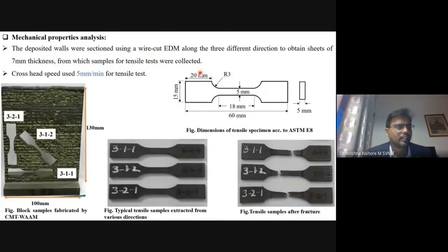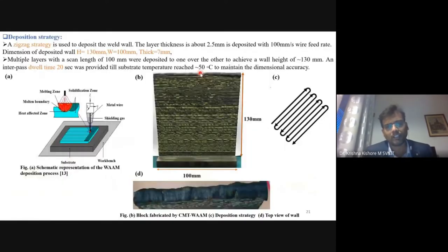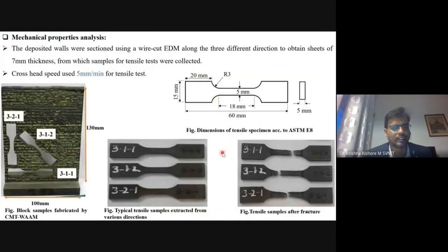Obviously, once we did these different depositions, we did them for at least different cases, like the weaving bead altered in different directions, right? And we did it in alternate directions. One layer will be deposited like this, the other layer will be deposited from the back, and in the other case we deposited parallelly. So these parallel bead depositions and everything have been characterized at a later stage.